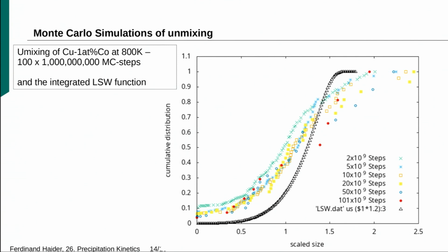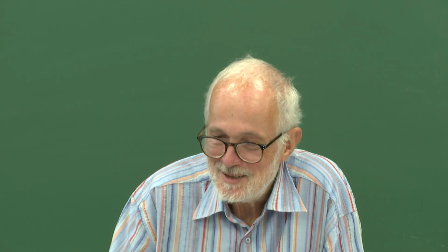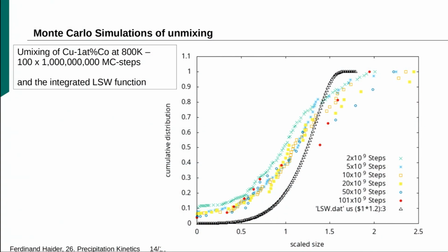I tried one other thing, and that's the point where I said I'm not 100% satisfied. I used these cumulative size distributions from before and put the LSW equation here in an integrated form onto these values here. And you see this does not fit nicely.